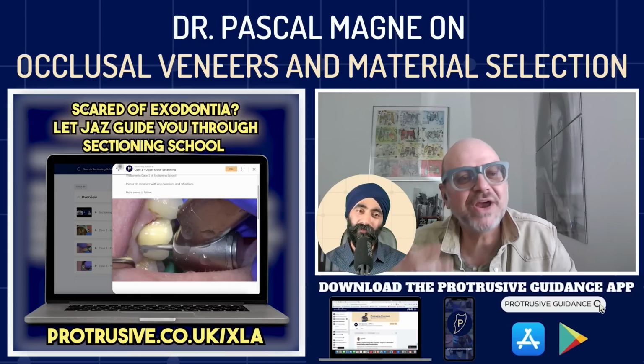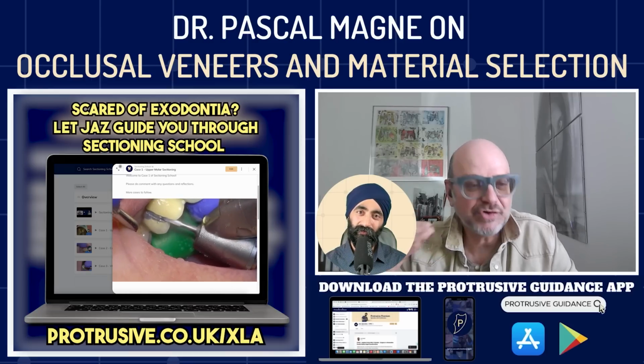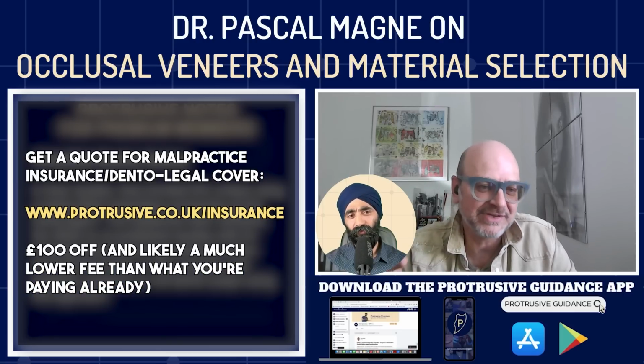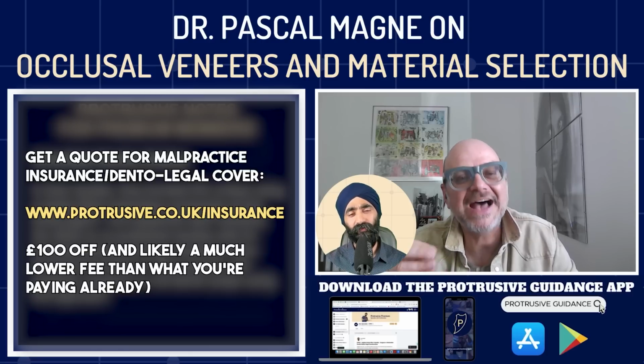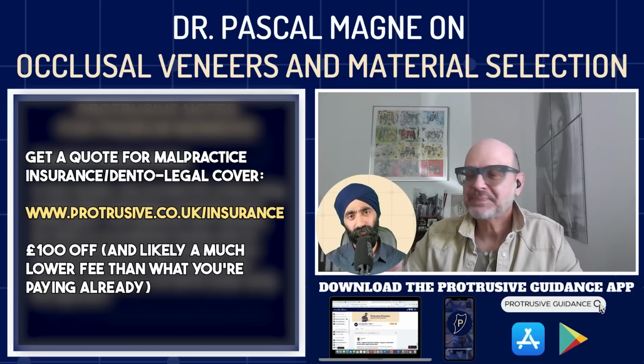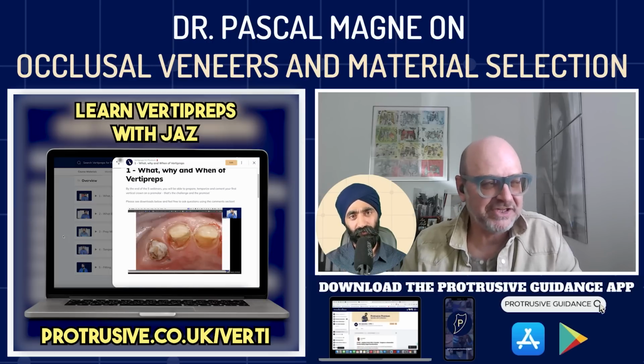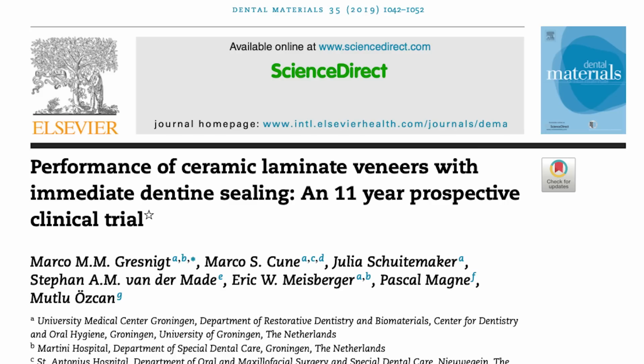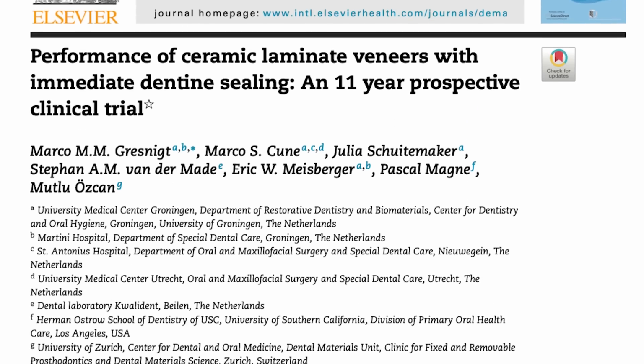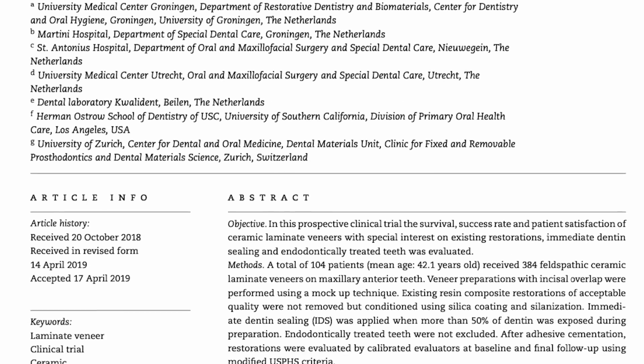And by the way, Jaz, that's another thing. When we are talking about those thicknesses, in our studies, not only did we use IDS, but we bonded those thin onlays with a highly filled restorative material. We used a restorative composite as a luting agent. And you can find those articles with Dr. Gresnigt that we co-published, where we looked at the strength of thin Emax veneers, anterior veneers, not posterior veneers, but Emax on full dentine preparations.